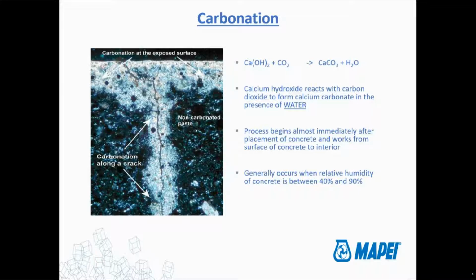So on the surface, it seems like a good thing, but as we'll see, it causes a drop in the pH. So even though you do get some marginal increase in the compressive strength, its ultimate effect is dropping that pH, which is of course not a good thing. But this happens really immediately. There's nothing we can really do about it unless you could somehow prevent air from coming into contact with fresh cement, which is almost impossible. If you're pouring concrete, it's going to be coming into contact with air. So that's a process that starts almost immediately once you mix your concrete and start placing it.